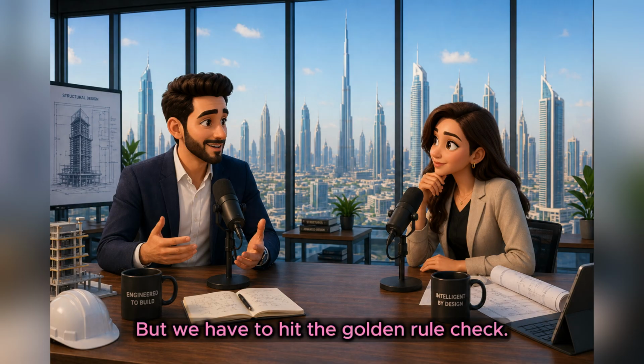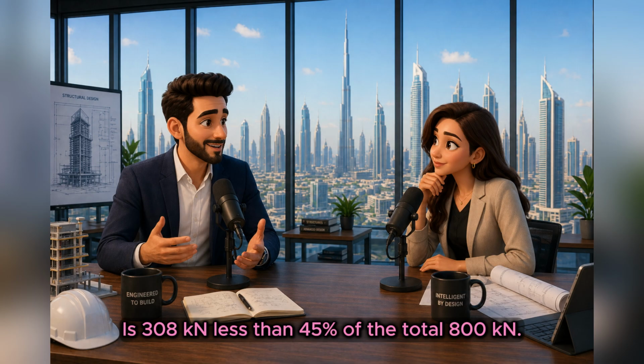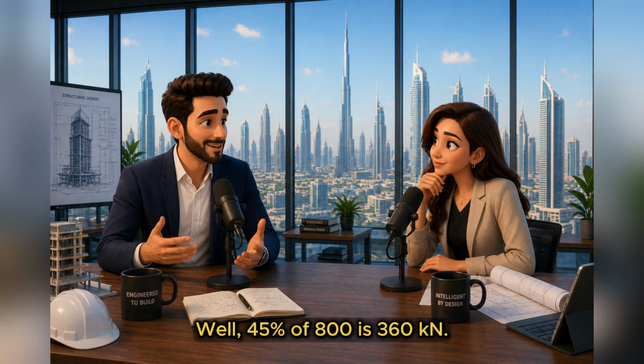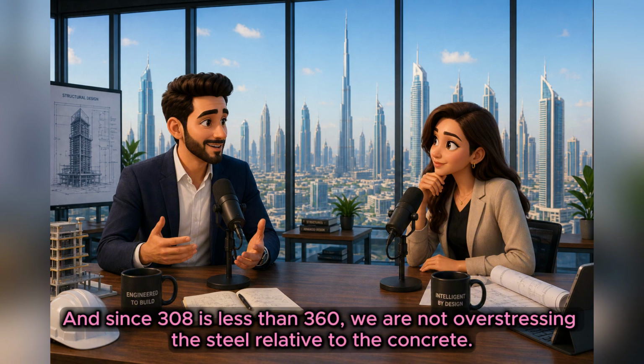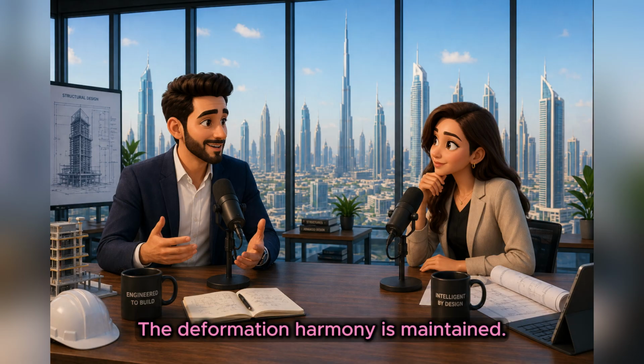But we have to hit the golden rule check. Is 308 kN less than 45% of the total 800 kN? Well, 45% of 800 is 360 kN. And since 308 is less than 360, we are not overstressing the steel relative to the concrete. The deformation harmony is maintained.